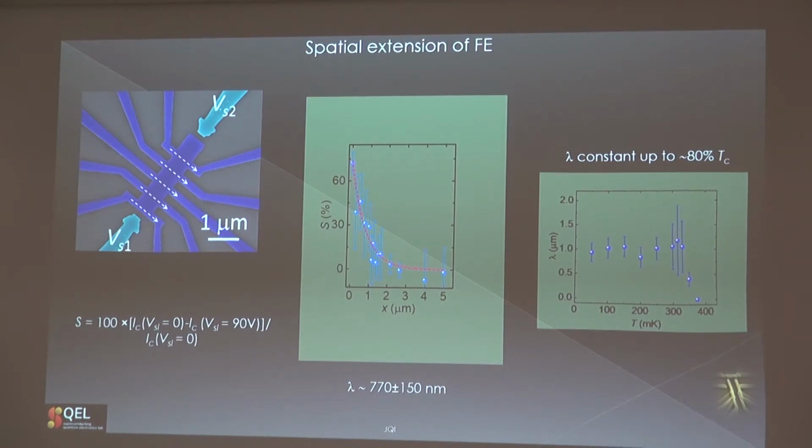And so whenever you heat one superconductor, this propagates, the thermal length is extremely long in superconductors, tens of microns, okay? Whereas here we have a very clear damping over a very small scale. So it's the first test to say, then if you ask me later, we can discuss the many tests to say that there is no heating, okay?